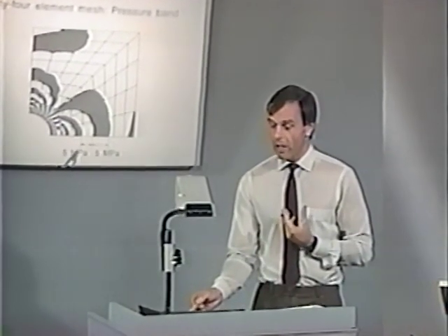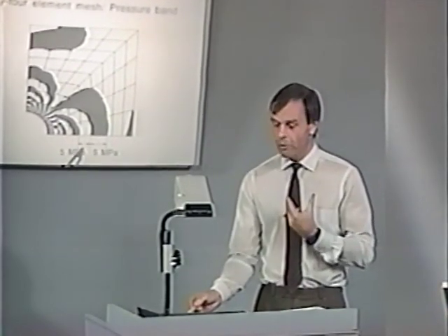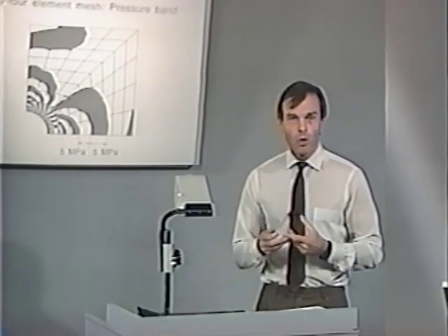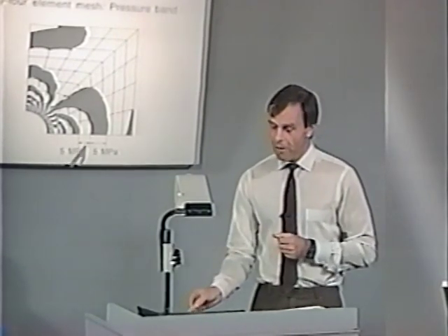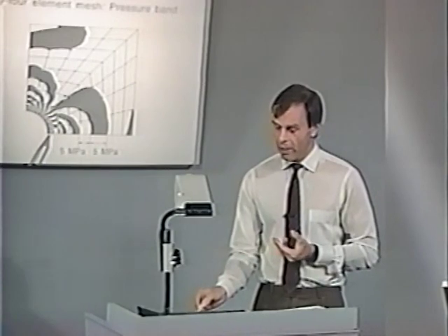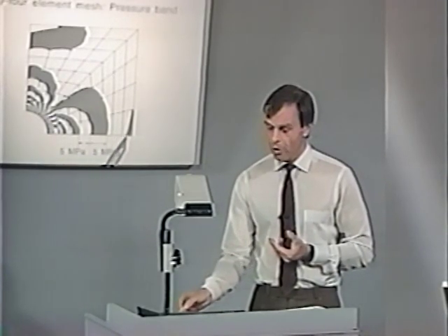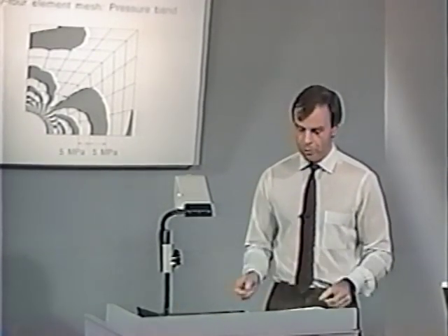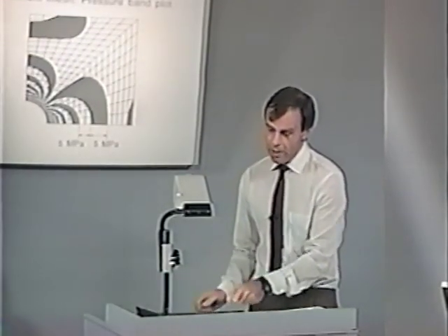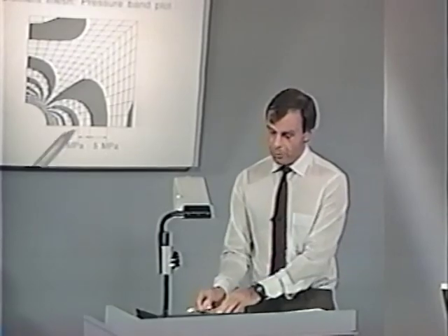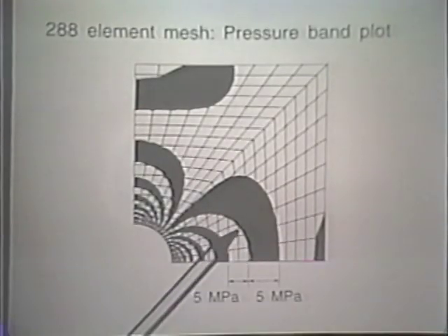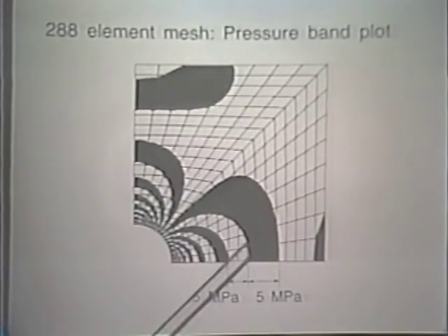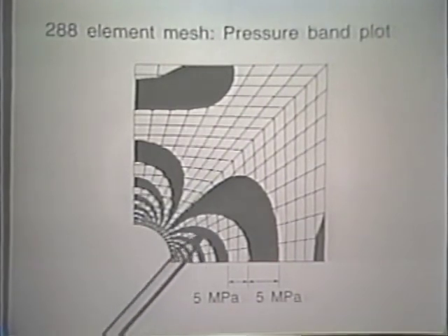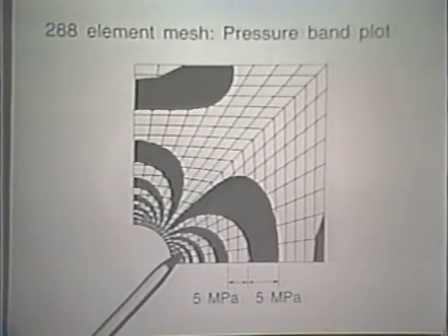You could also select 10 MPa. Of course, then that would be a very loose criterion. And 5 MPa for this particular problem, since you can see we're getting quite a number of bands along here, is a reasonable way to proceed. If we go to the 288-element mesh, the pressure band plots look like this, beautifully smooth. You can see here the smoothness in the pressure band, no discontinuity at all.